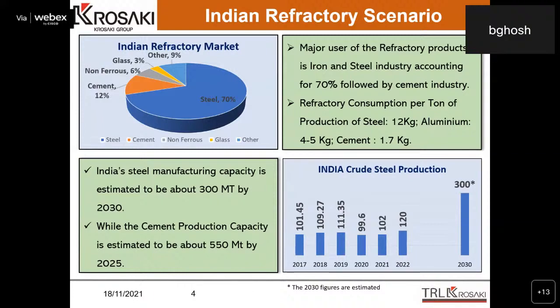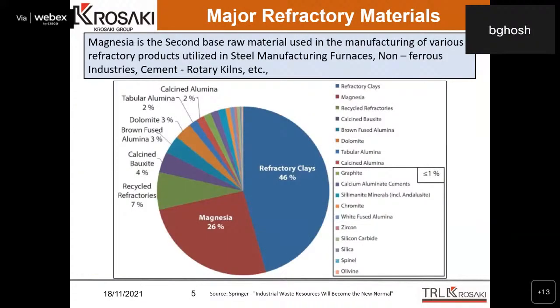By 2025-26, the refractories market is planned to grow at the rate of 5% of the total global market, touching around 12,000 crore for the Indian refractory market. The major refractory raw material, as you know, is magnesia, at around 26%, and others, if you see, are refractory grade clay, then calcined bauxite, brown fused alumina, dolomite. This is in the total pie. The 26% of magnesia is being consumed by the refractory producers for steel manufacturing and non-ferrous sectors. So this is the most important area that we are catering to in the refractories market.